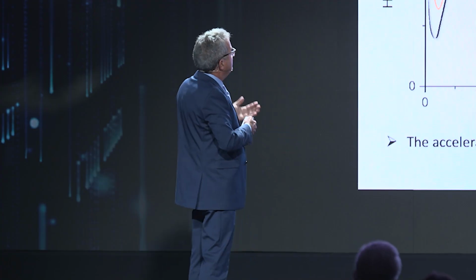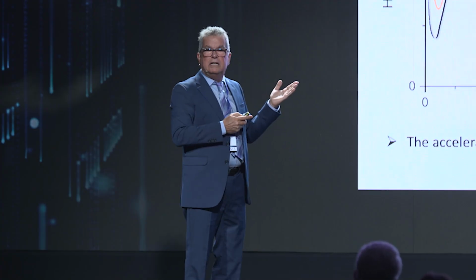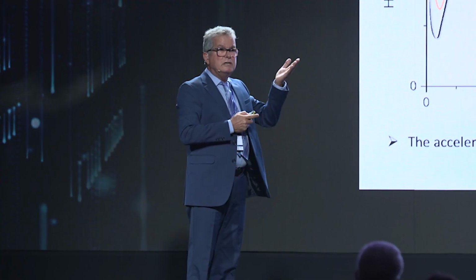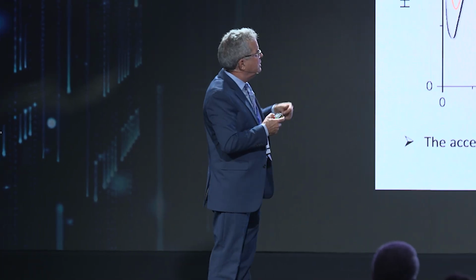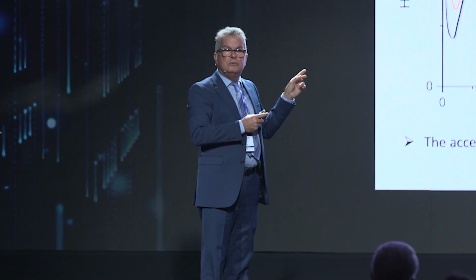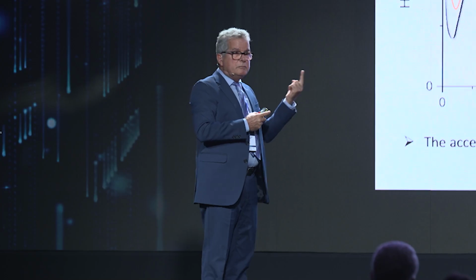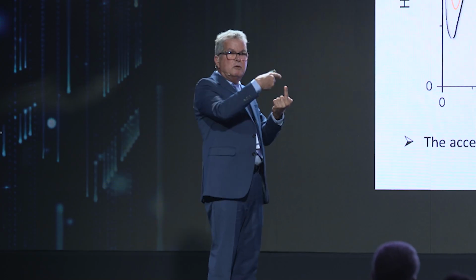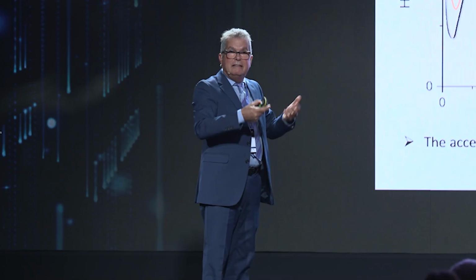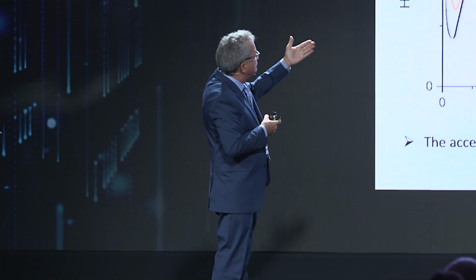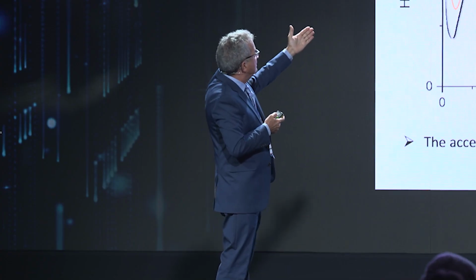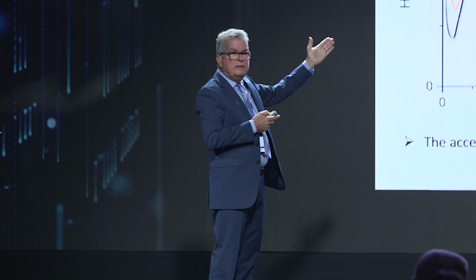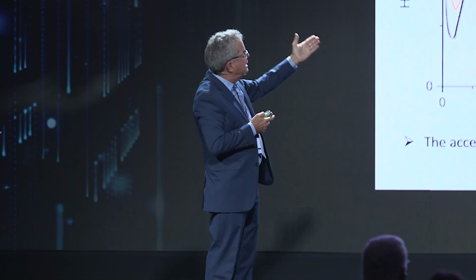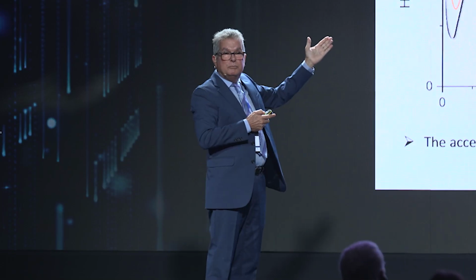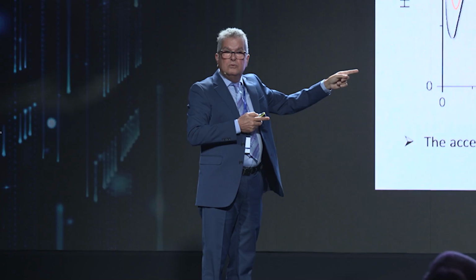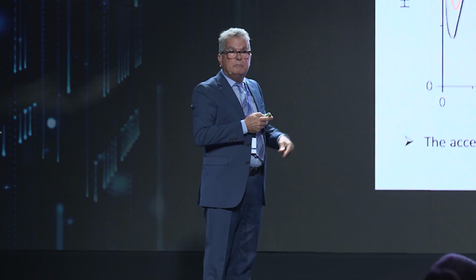But I can tell you, if you have a clay with a low kaolinite content and you want to boost the reactivity of this clay, like you see here, one of the things you shouldn't do is to do color control, because the presence of iron creates some amorphicity in the system that enhances the reactivity of this material, and this is already proven. You see, we're talking about a clay here that has 47% kaolinite content, and another clay that has 72%, and this one, if you don't do color control, you can improve the reactivity.